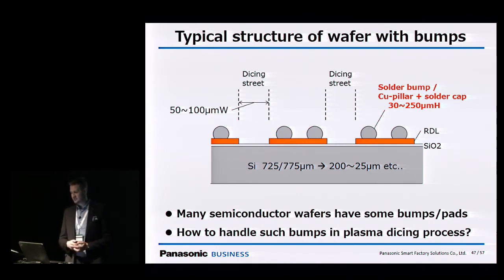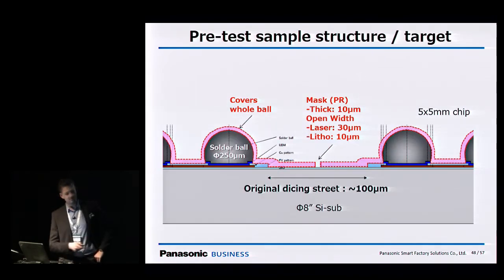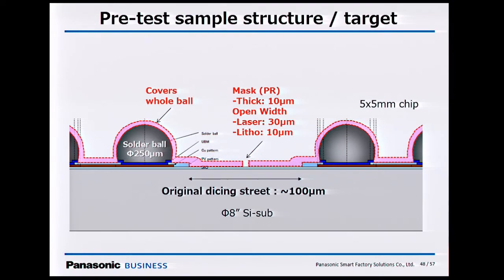So this is a kind of test wafer that we received. We wanted to set our target to prove that if we do a photolithography method, we can conformally coat 10 micrometers all the way around. And then we can dice using laser patterning with 30 micrometers street width and lithography of 10 micrometers. This is getting a little bit old, it's about 1 year, so we've beaten this. We're down to 20 and 5, even lower.